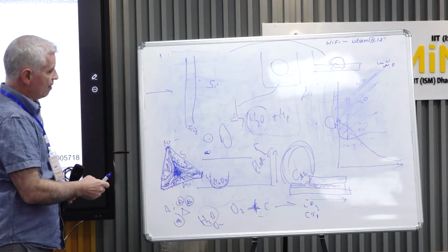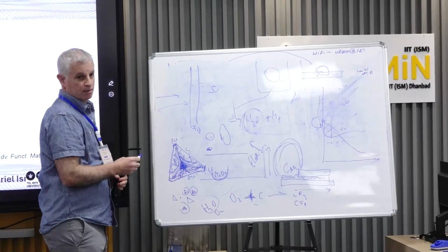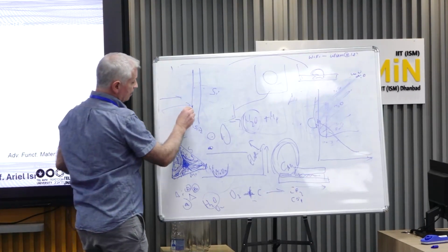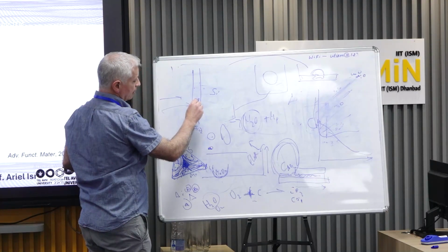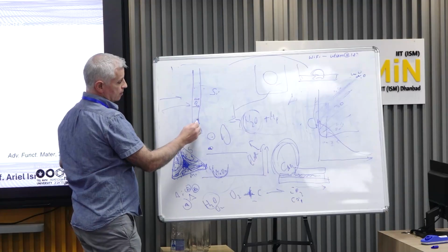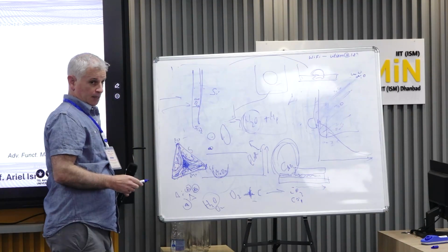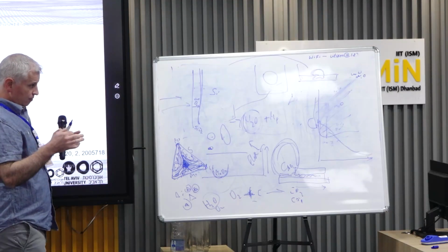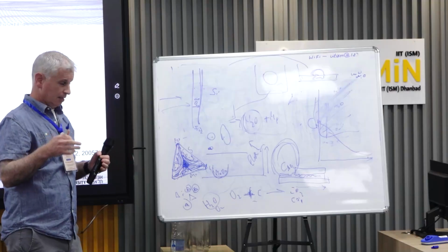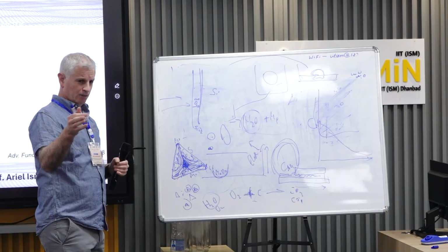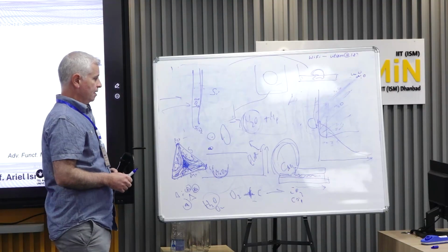So basically you have three regimes: the gas flow to the substrate, the diffusion of the oxygen entities towards the interface, and then the reaction. Right? This is the basics of the modeling of thermally grown silicon dioxide. You can find it everywhere, the Deal-Grove model.